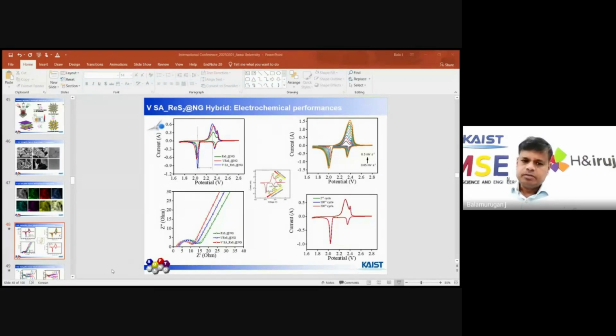We also do impedance spectroscopy, with the real and the imaginary parts. I forgot to put the minus sign in the imaginary part. This is the RS value, the solution resistance, and this is the RCT. This RCT is lower, and this one at lower frequency is the ion transportation. The ion transportation is better for our single atom catalyst than the other comparative catalysts. And for durability, you can see before and after the second cycle and total cycles, both the oxidation and reduction peaks are almost maintained. From the studies, we can conclude that our catalyst may help enhance the durability.